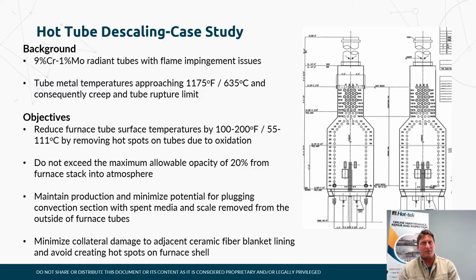But in this specific one, we can also blast 1 1/4, 2 1/4, 5-chrome tubes. Really, the metallurgy doesn't affect us. What we will see is that you'll see more of a tree bark growth on some of the lower chrome content tubes, where we are getting quite a bit of very, very high temp pieces of metal or oxidation that have come from the tube.